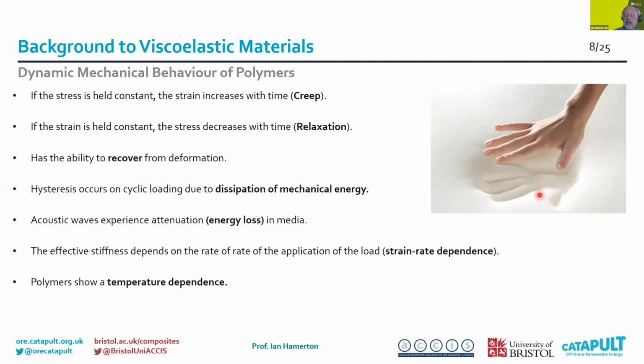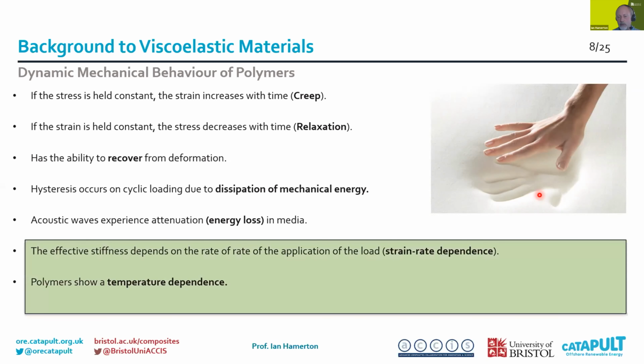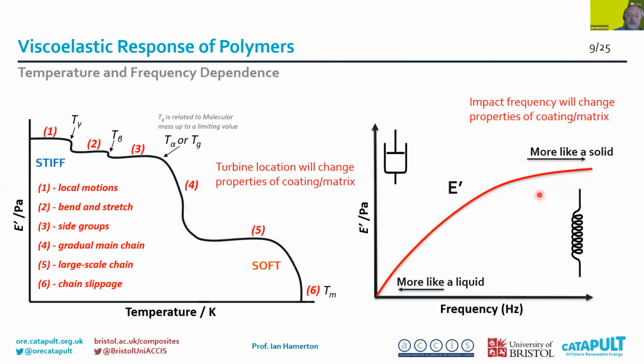So these materials are quite dynamic, and that in itself presents quite a different idea in terms of how we test and evaluate them. So this strain rate dependence is key, as is the temperature dependence. So not only is strain rate key, but temperature of analysis is also important. And you can see that in these classic schematics showing how those properties change. So on the left-hand side here, you'll see this is looking at essentially elastic properties, modulus against temperature, for a typical viscoelastic polymer. What you'll see is, whilst we're conditioned to think in terms of what we call the glass transition temperature, where you change from a glassy to a rubbery material, there are also a series of different changes where you get molecular motions, be they small, short scale, slightly larger, longer scale changes, and effectively slippage in polymer chains